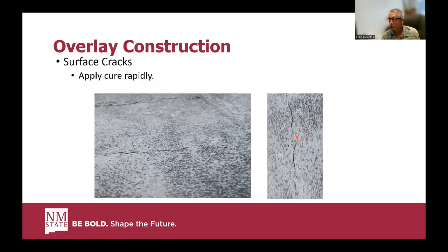Talk about cracks, and in that first portion of the first placement, it's the same crack in both pictures, but that's basically what the cracking looked like. And it wasn't tight. I mean, you don't see any other cracks in this photograph, which actually encompasses quite a bit of area, but it was just moderate. It wasn't isolated, but it was not densely cracked either. And it really just needed the plastic to come down on top of the curing compound more rapidly.